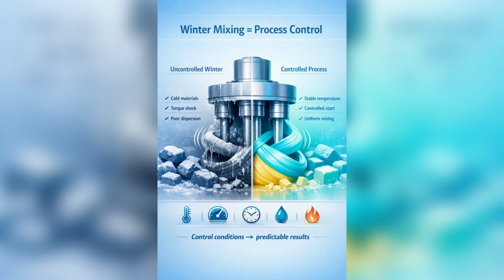So the winter strategy is clear: standardize the starting temperature of materials as much as possible, control initial rotor speed to avoid torque shock, allow proper mastication before heavy filler loading, keep oils and fillers thermally stable and dry, and warm up the mixer to a consistent baseline. When you treat winter as a process control issue rather than a formulation problem, the same compound behaving differently becomes predictable and manageable.